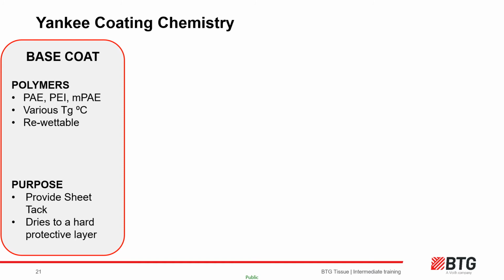One function of a base coat is to adhere the sheet to the Yankee to ensure close intimate drying on the cylinder, good sheet control off the Yankee whilst maintaining and generating crepe bars when the sheet is forced off the Yankee by the creping blade. Its other function is to develop a hard layer to protect the Yankee surface from erosive and corrosive wear and also adhesive wear, sometimes called micro welding, from heat and friction generated by direct contact with steel from, for example, a steel creping blade.